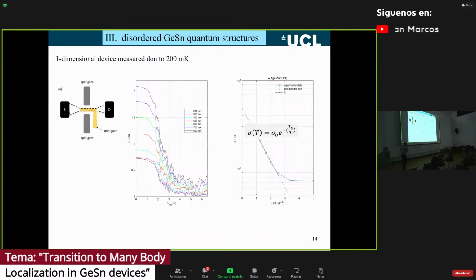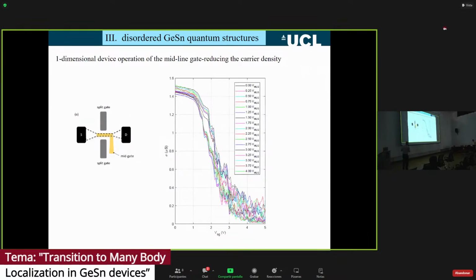If we plot out the conductance, this conductance here is at 0 split gate voltage. So it's just the 2D conductance, which is thermally activated. The question is, once we form a 1D system, do we still have that same thermal activation? So this is plotting the device conductance as a function of split gate voltage, where we reduce the carrier density by putting a depleting voltage on the midline gate. As we put a depleting voltage on the midline gate, well, we've got Coulomb blockade in there, but we've got a real mess. And people again would say, that Stuart Holmes person, he doesn't know how to do measurements. This is all just noise.